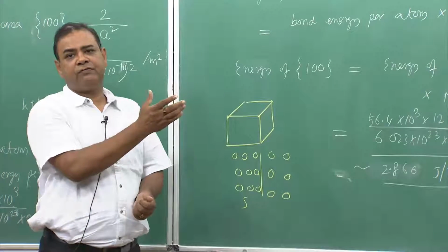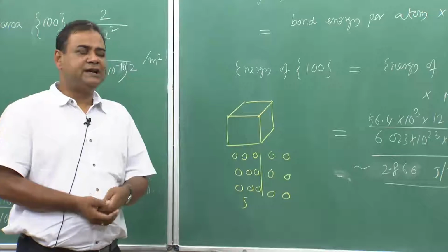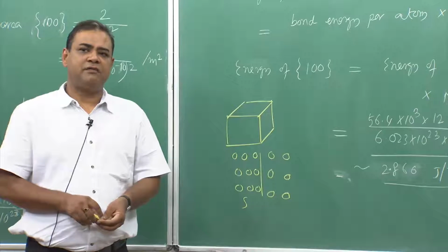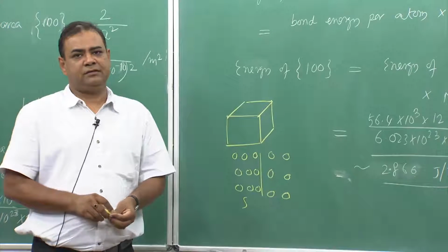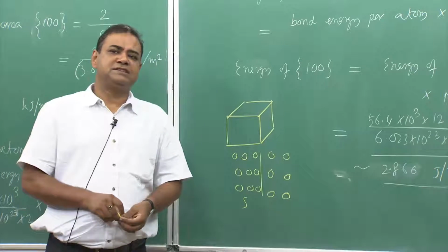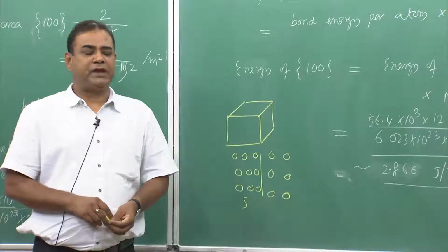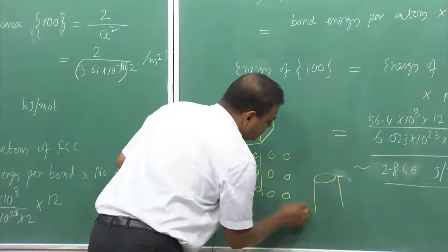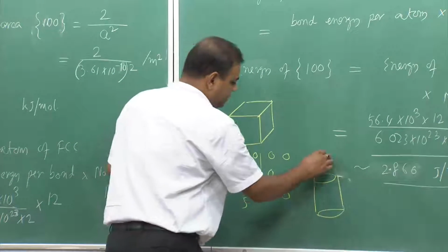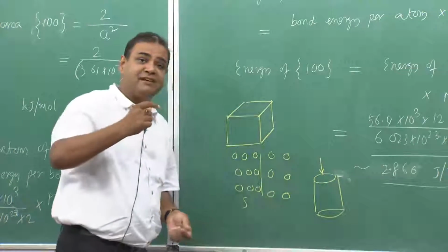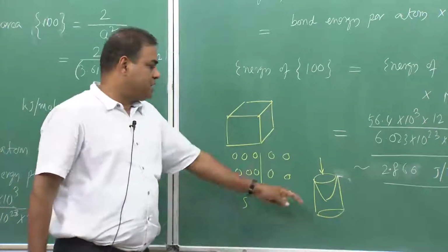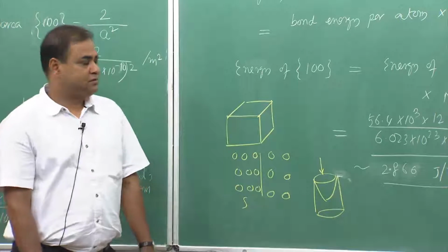And whenever we have a liquid to solid transformation, there is a decrease in volume, and this decrease in volume is the culprit for shrinkage damage during casting. So, if we see several casting defects, one of the major defects is piping. So, let us say we want to pour through this particular section. Now, if we pour, the liquid metal, because of that shrinkage, because when it solidifies it decreases its volume, you have a kind of cup kind of thing. So, that is coming due to shrinkage.